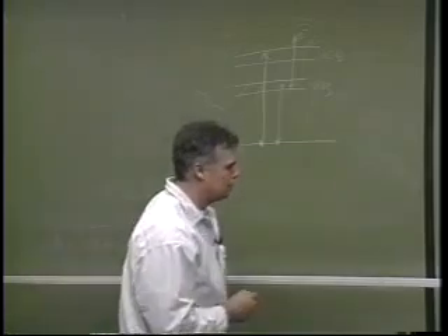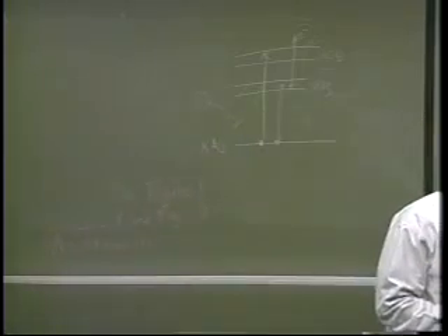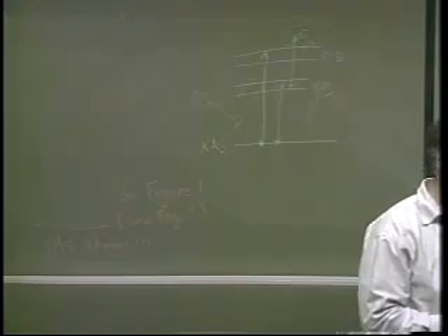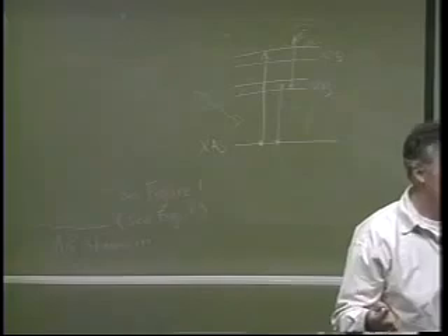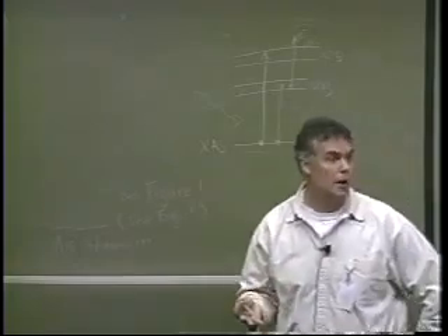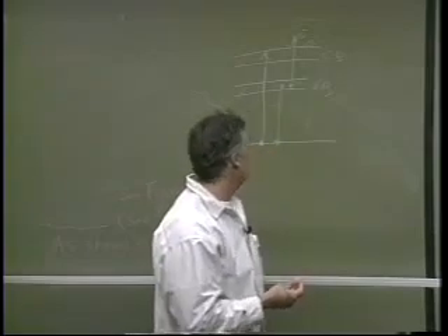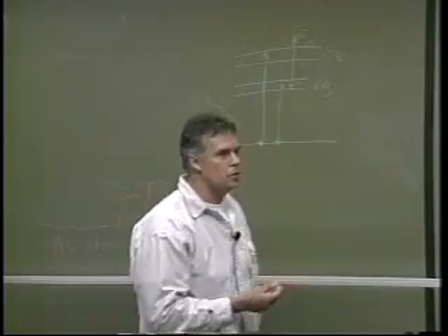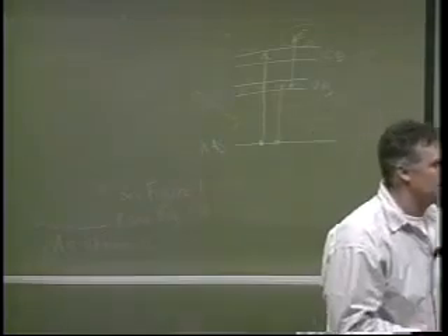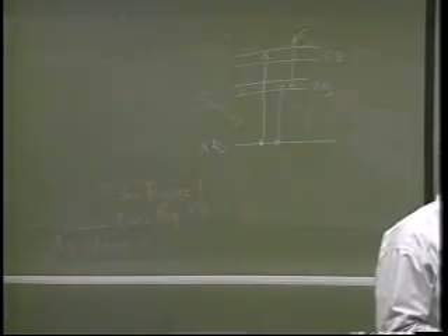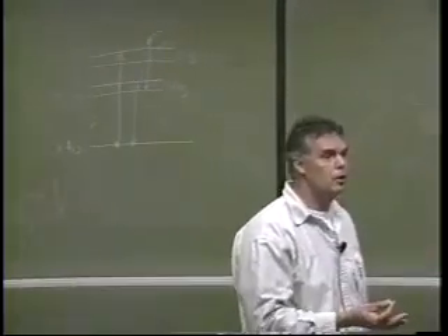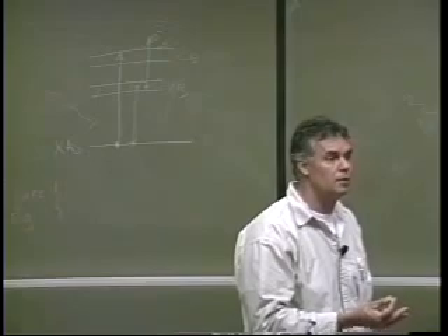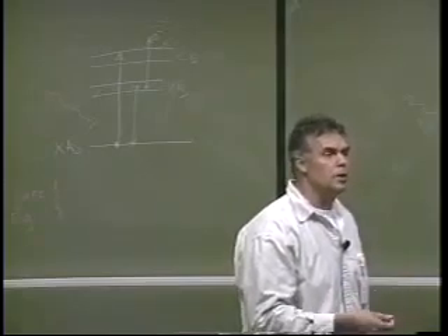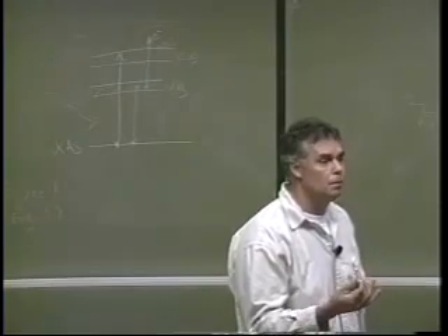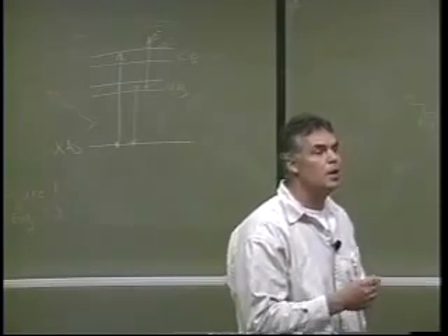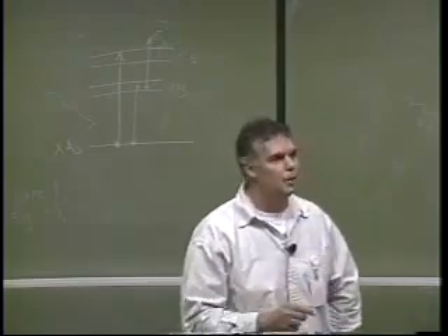Well, it is true that for the higher Z materials, for K edge and L edge, the fluorescence yield is actually quite a bit higher. And I believe that in one respect, at the lower energies, and this is perhaps a cop-out answer, it's just more favorable for the Auger process to happen. I think to one degree you have so many electrons in the delocalized valence band that's close that the Auger electron coming from a valence band has a tendency to knock out more secondaries and cause a cascade process, quenching core holes easier. Now that's a bit wishy-washy.